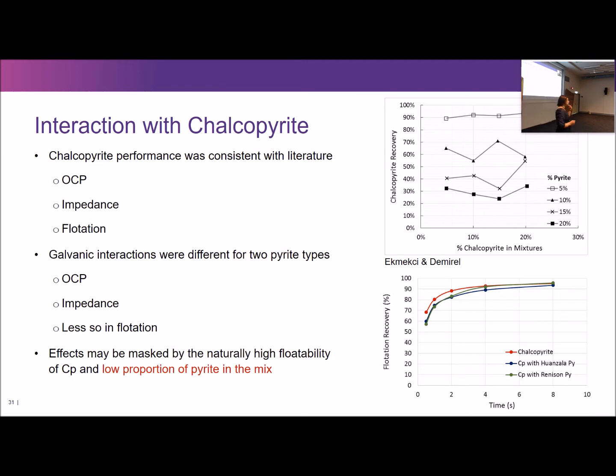However, if we were to increase the proportion of pyrite in our mix, we know that it would dampen the flotation of chalcopyrite even more. And it may then produce a much more significant difference in chalcopyrite flotation dampening from the 2 pyrite types. Sadly, this is what happens when you're a bit constrained on resources. When you do this kind of work, you simply run out of money and you can't confirm the findings. You badly need to confirm it. It's very sad.